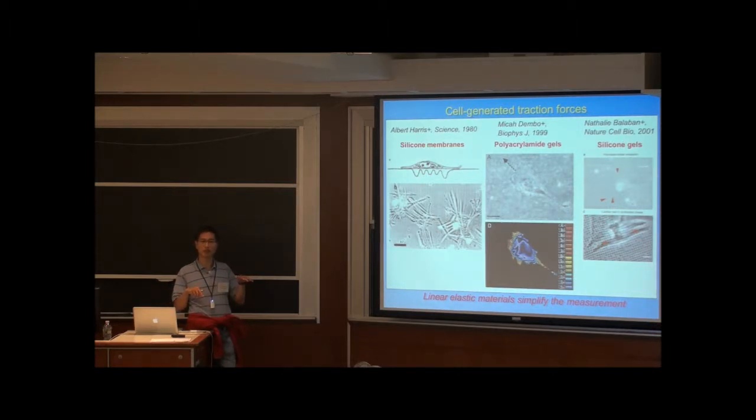Does that make sense? So what he did was he fabricated onto the surface of this silicone regular dots. So now you don't really have to track them because you know where they came from. They used to be aligned, and now as they move out of a grid, then you know what kind of deformations there were. So this simplified the tracking problem.